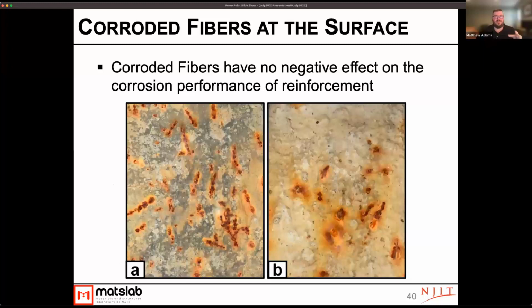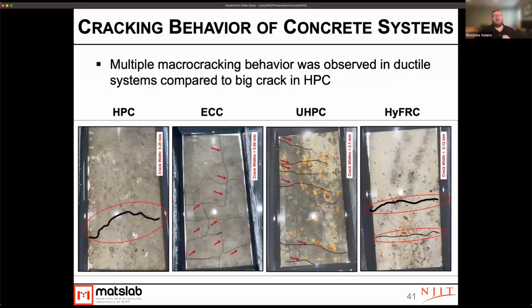We do see some corrosion in the fibers, the metal fibers at the surface. This is typical. However, this doesn't necessarily mean that corrosion has moved through the system. These are just fibers that were already exposed at the surface. And then these are our systems after we cracked. And so you can see for the HPC system, we get one large crack, whereas for the ductile concretes, we tend to get more distributed cracking pattern and smaller cracks.